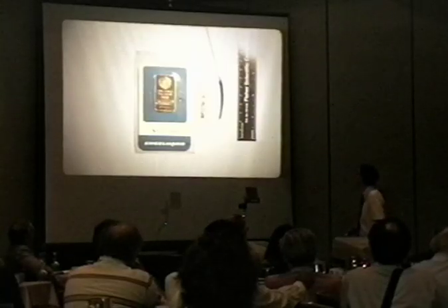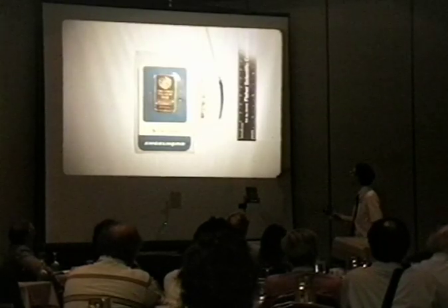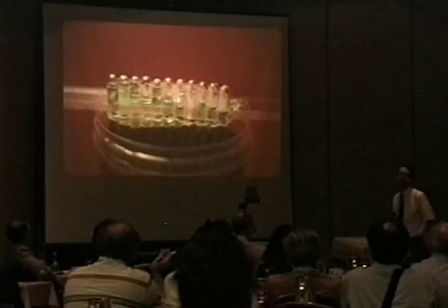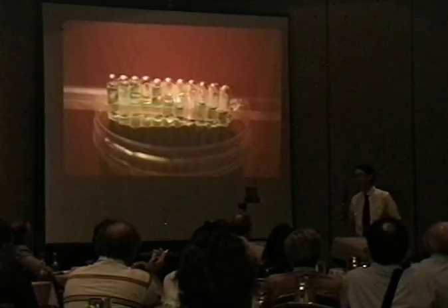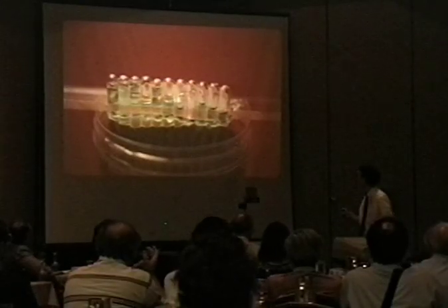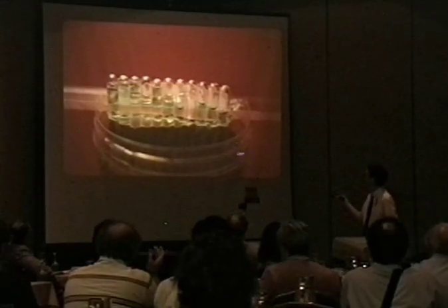But finding a proper piece of palladium is very critical to the experiment. I physically take this and put it under a microscope, look for obvious defects, if it has lead lines, things like that, and do not want to use it. Another way that I select is by the bubble pattern. Mine are clear systems, and I've noticed that when I have a very uniform bubble pattern, uniform grain, it seems to work, so I want to have some quantitative measure.